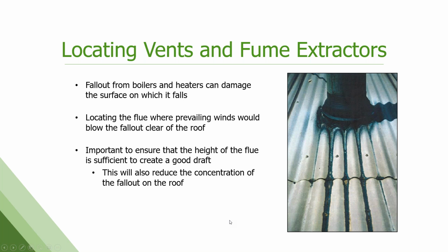Vents and fume extractors: we talked a little bit about the temperatures that this product can stand, but in addition to that, it's any fallout. Any particulate matter that's coming out of a vent, fume hood, or extractor could be problematic. You want to make sure it's not corrosive. You want to place the vents such that the prevailing winds blow that away if possible, and that they're high enough that the discharge clears the roof as it dissipates and doesn't fall right on it. What we have here is a picture of what not to do. That black you see running down the panels is actually corrosion of the aluminum component. It's oxidizing that aluminum to black and eating through that metallic coating because of what's coming out of that vent.